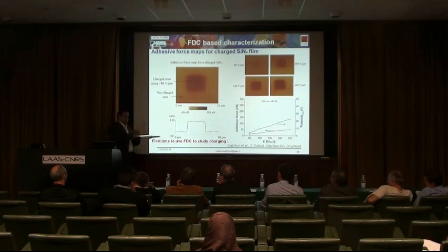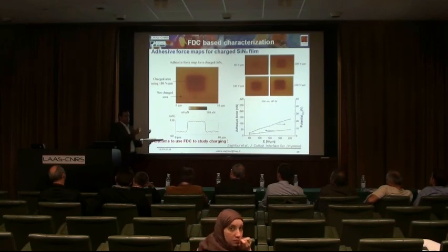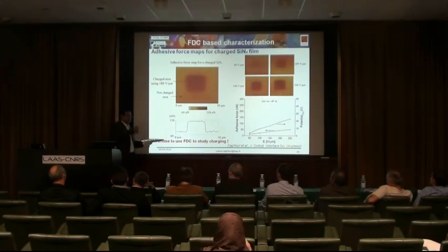Number one: when you start scanning, because of the electrostatic force, since you have a biased tip, this contact force increases. There is another option where you can control the contact force so the electrostatic contribution could be cancelled during this exchange. An important issue here is that if you inject using different contact force, you have different charging, because the apex of the tip is changing. So you have different charging areas and time and so on. This is the first message: you can control the contact force.